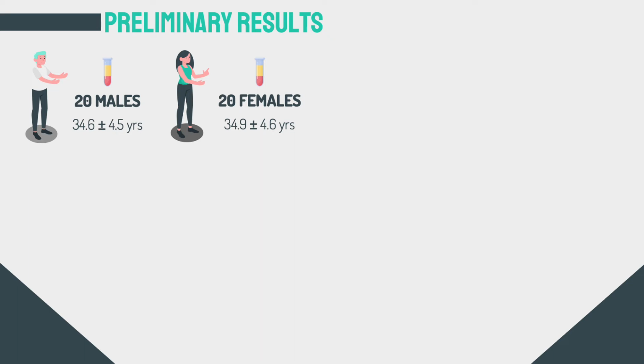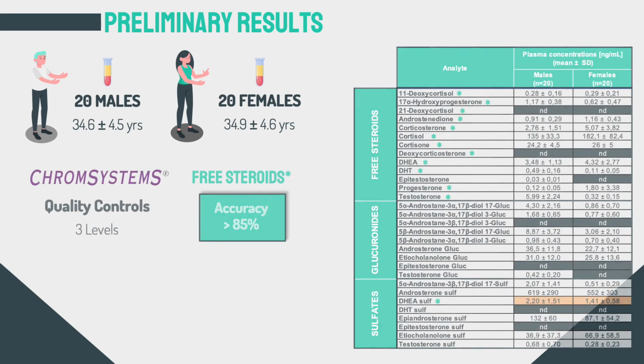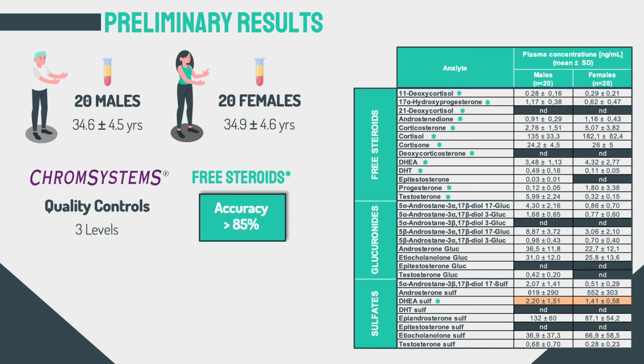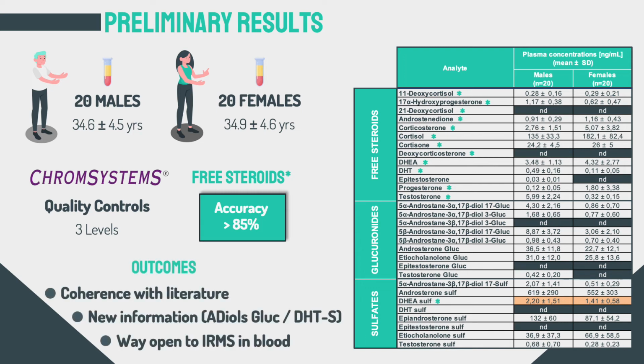The obtained results, expressed as mean plasma concentrations, are presented in this table, and the method's quantitative performances were checked by injecting in each batch of analysis quality control samples, part of a commercial LC-MS kit by Chromsystems, which gave satisfactory accuracy outcomes. The concentration measured in this study showed good coherence with reference intervals already reported in literature, most of them referring to free steroids,